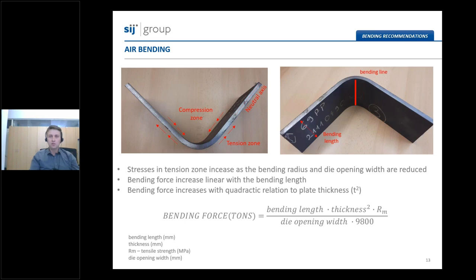The bending force during the bending can be approximately calculated using this equation, which is written on the slide. We just multiply the bending length, the thickness squared, and the tensile strength. And then we divide this result by the die opening width and the number 9,800. And what we get as a result is the bending force in tons directly.